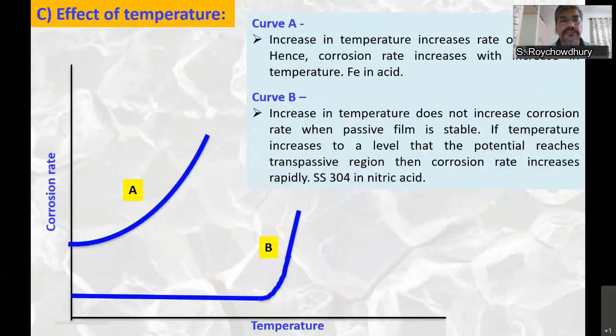Effect of temperature. Again, two possibilities. Possibility A, where you see an increase in temperature will cause an increase in your corrosion rate. This is understandable because increase in temperature will always increase reaction kinetics. So the corrosion rate will also consequently increase.